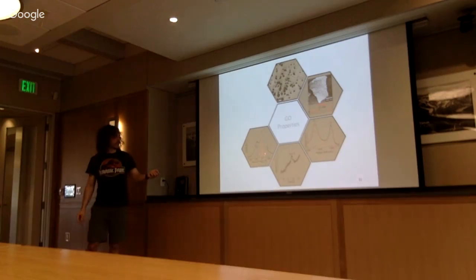And then another important technique to characterize graphene oxide is X-ray photoelectron spectroscopy, XPS. So basically here we have binding energies that are unique to specific bonds. And we can see that the graphene oxide is really oxidized, and we have epoxy and hydroxide groups at about 287 electron volt. And we have double bonds, mainly carboxylate, at 289 electron volt. We can also do some Fourier transform infrared spectroscopy, but this is not really quantitative, so we stick mainly to XPS.